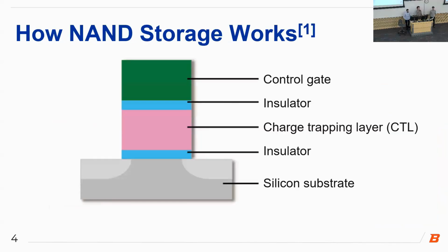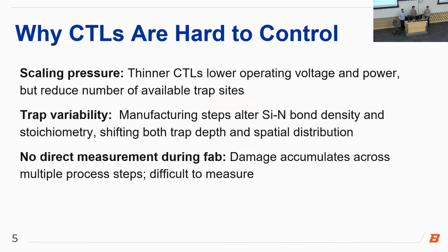So to give you a quick idea of how NAND works, by applying a high voltage to the control gate, electrons can tunnel through the insulative layer into the charge trapping layer. When that voltage is removed, the charges are retained in that charge trapping layer. By applying a low voltage to the control gate, electrons may or may not tunnel based on the threshold voltage that is affected by the trapped charges. To remove the charges, you can apply a high voltage to the substrate to essentially pull them back out.